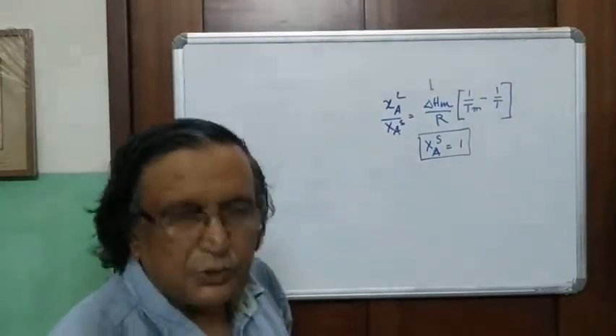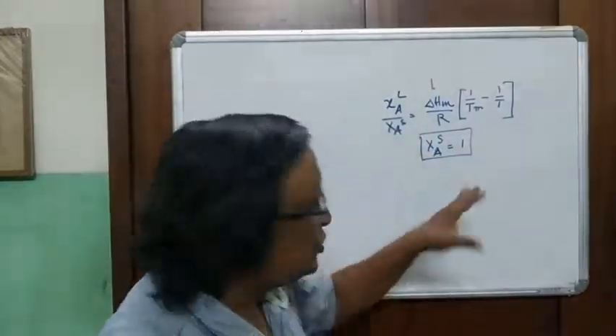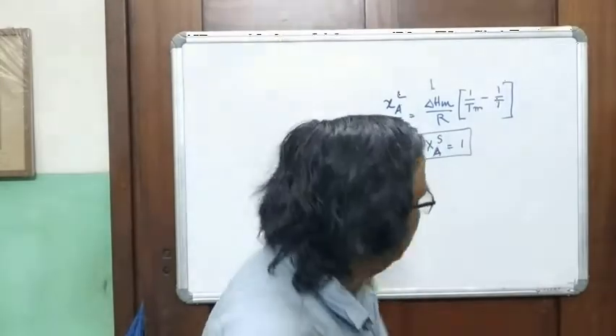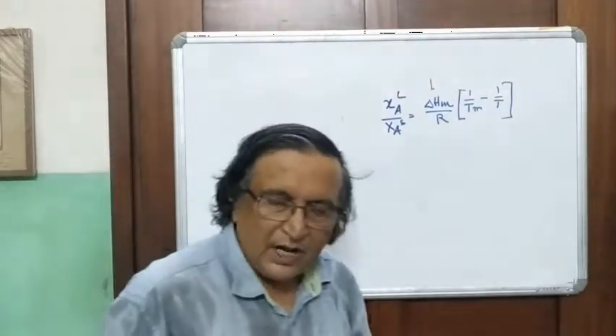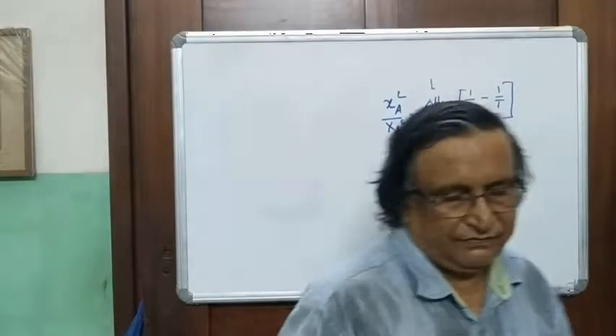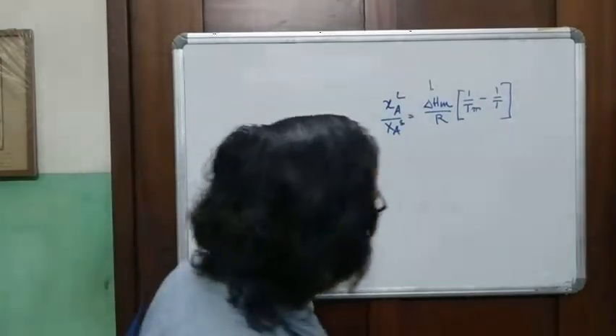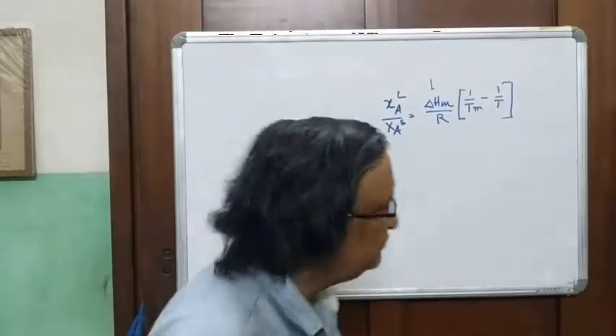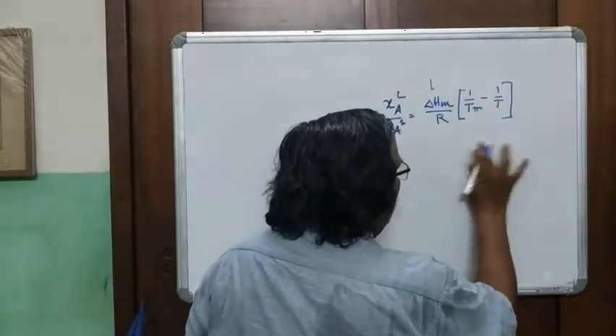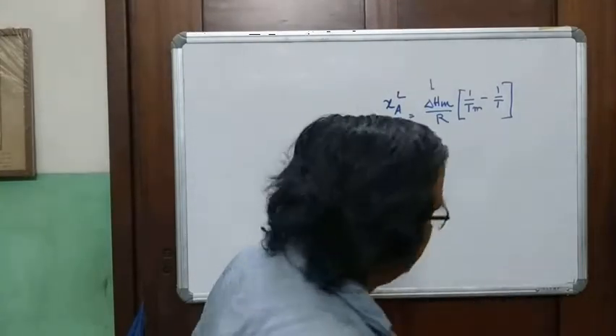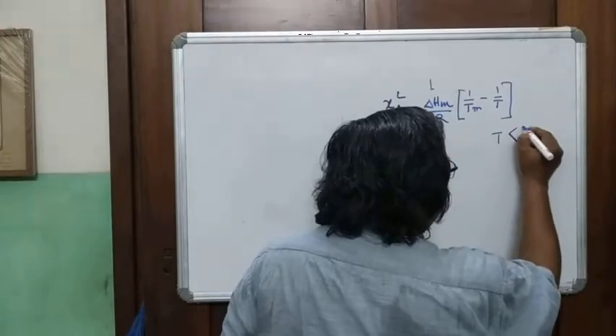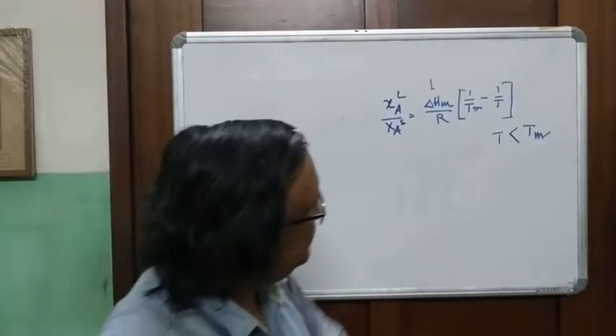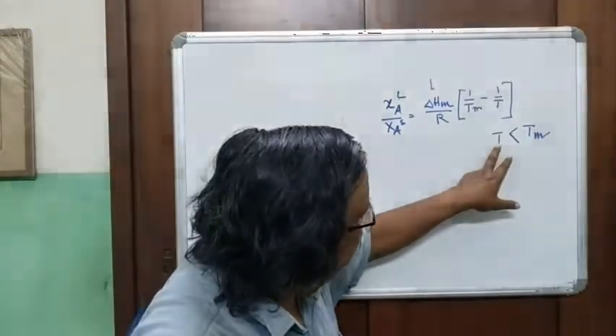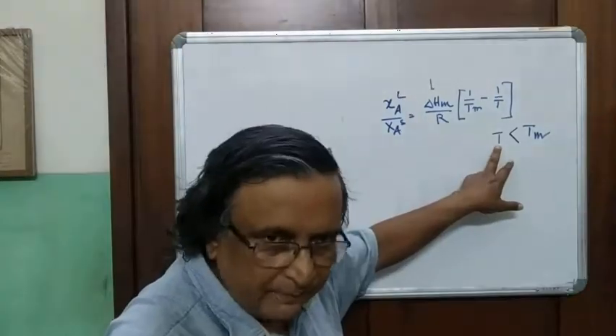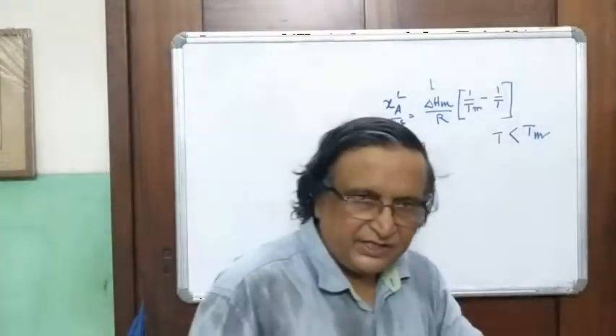Now, we do not do this. We also take in what happens to the phase relations if XAS also has a value not equal to 1. And you know mole fraction will have a value which is either 1 or less. So now we look at the equation once again. We all know from our crystallization sequence that we studied, T is less than Tm, where Tm is the melting temperature of the pure phase and T is the temperature of the equilibrium, which is lower than the melting temperature of the pure phase.